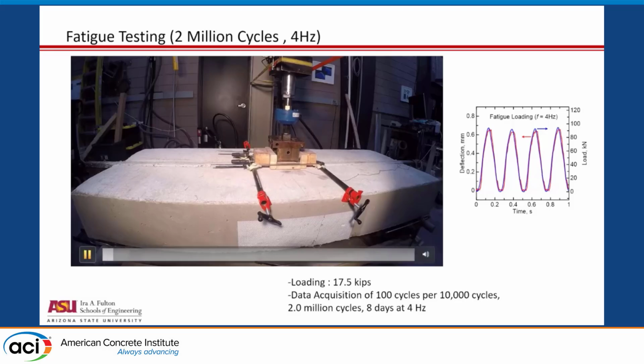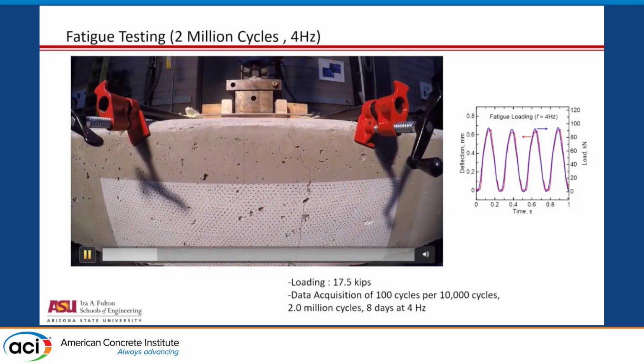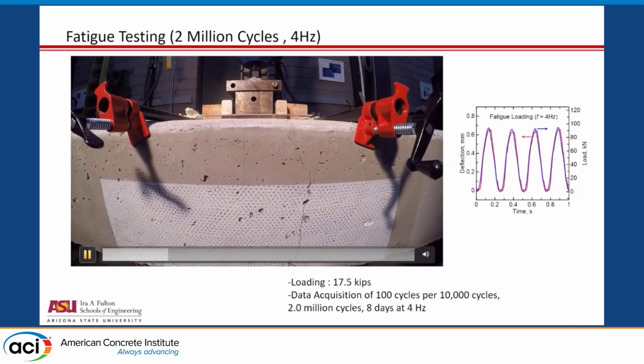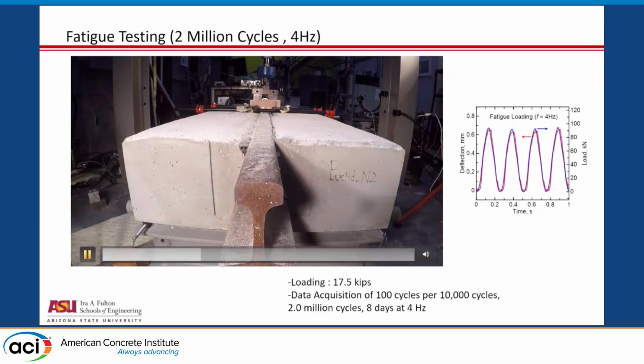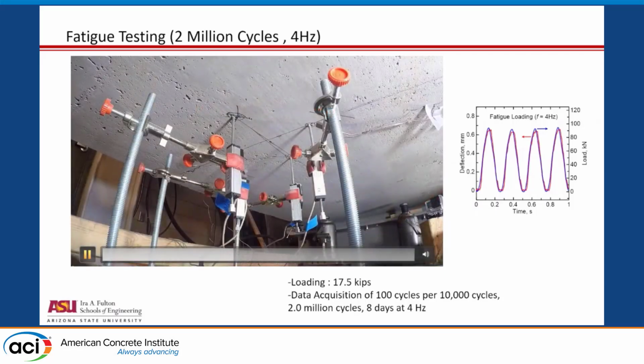So we can also look at now, then we conducted the fatigue tests, and in here we're going through 2 million cycles. And as we go through these cycles, at every 10,000 cycles, without pausing the test, we collect about 100 or so cycles. So first the specimen is cracked under load, and we're doing the fatigue in a post-crack type of environment. And that provides the loading that we have. And everything is still in the elastic phase, other than the concrete that can crack.